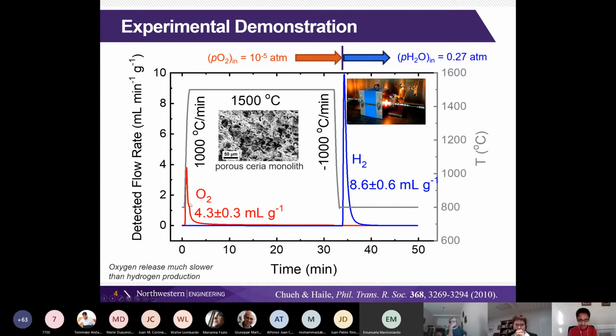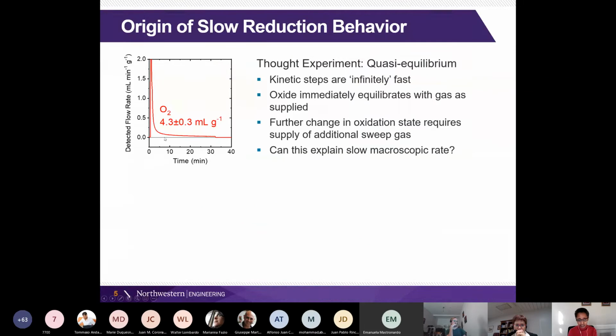One thing to notice here is that this oxygen release is indeed slower than the hydrogen production. And to some extent, you might think, well, if this is kinetic, some sort of bulk diffusion or surface reaction rate limited, you expect things at high temperature to go faster than things at low temperature. This is at 1500 and this is at 800. So let's see if we can understand this relatively slow oxygen release. So this is just zooming into that. And we did the release for 30 minutes, and this is where we switched over to lowering the temperature. So it takes this full 30 minutes and it continues going on.